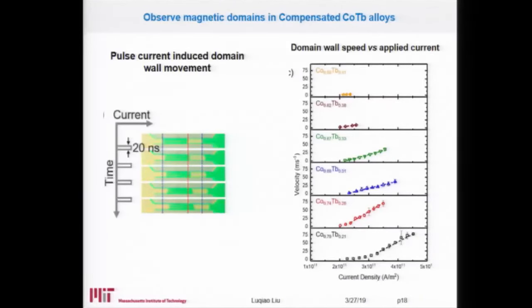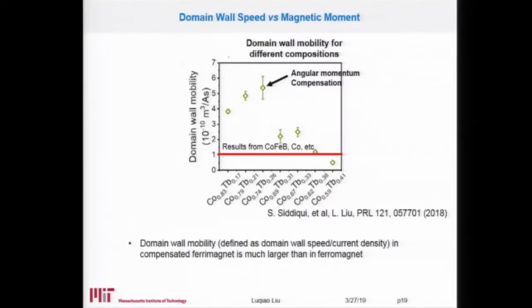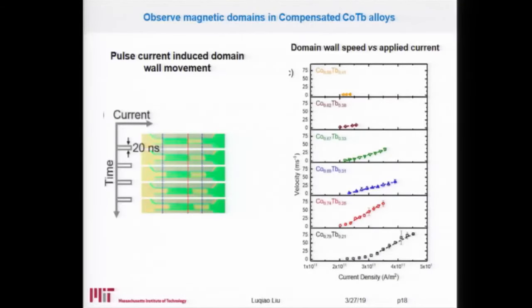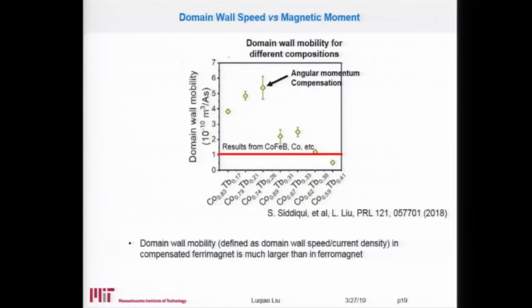As you can see, across different compositions of cobalt-terbium alloys, we get different slopes that reflect different domain wall velocities. And finally, if we summarize the domain wall mobility, which is defined as the slope of those curves, you can find that there is one specific composition that has the fastest domain wall velocity. It turns out that this one corresponds to zero net angular momentum. So by using this multi-domain device, we demonstrated that there is a speed advantage associated with materials with zero net magnetic moment. And if you compare with traditional ferromagnetic materials like cobalt or cobalt iron boron, you will see at least a factor of 5 improvement in the domain wall speed.